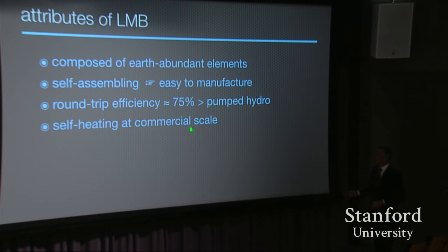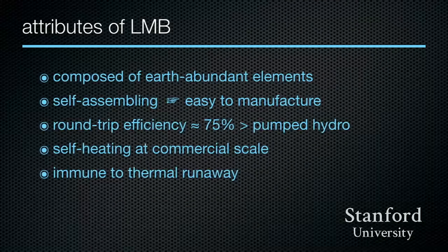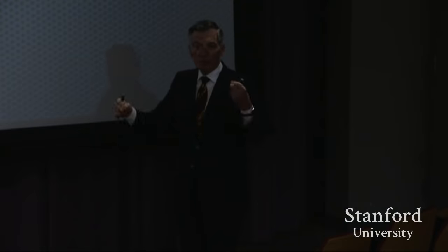And at commercial scale, it's self-heating. Our cells in the laboratory are tiny, so we have external heaters. We don't worry about thermal runaway. In fact, we've shock tested these where we actually mix the top layer with the bottom layer. Got a huge exotherm. Temperature goes up, but below the melting point of the steel can and below the boiling